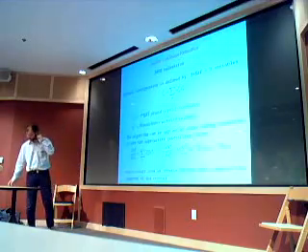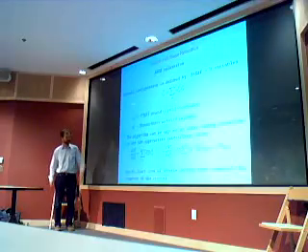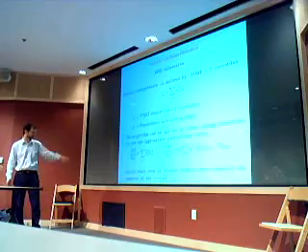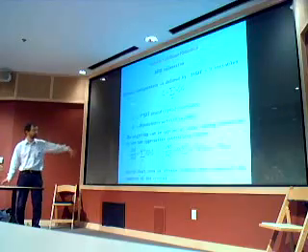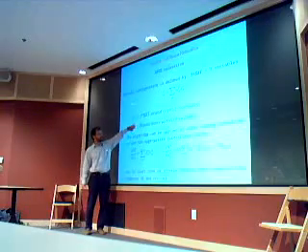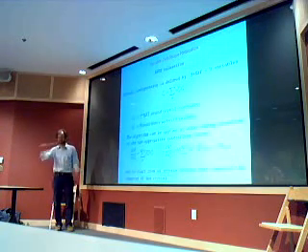And the other thing that you need to do, if you want your relaxation to preserve the symmetry, is to start with an inverse Hessian that has the symmetry that you want to preserve. So usually, in the usual case where Bravais lattice vectors are not included and Cartesian coordinates are taken into account, one starts from a diagonal Hessian that contains no information.